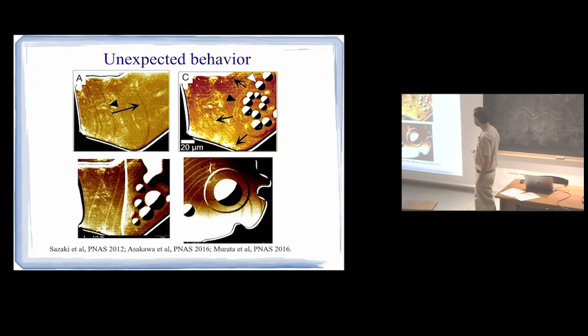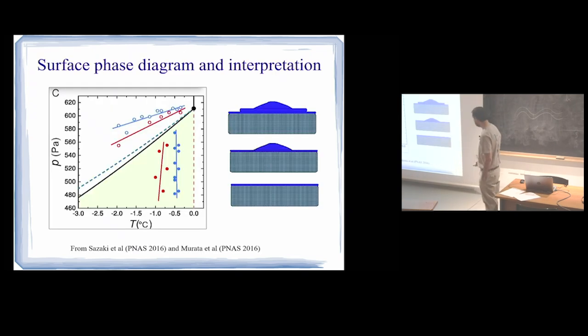They could see from their pictures that this clearly is a liquid film. So they said, okay, at equilibrium there is no pre-melting. Pre-melting only emerges at sufficiently high saturation. And they thought, this must be the pre-melting. Okay? But anyhow, the situation is that they could map their behavior on the surface phase diagram. There is this broad region in which they just see a smooth surface. They would claim it's the bare ice surface. I claim that there's a pre-melting film on top of it.